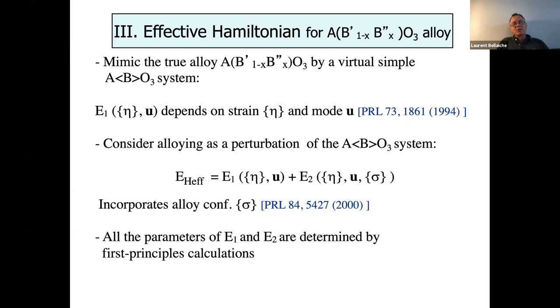And then we said, no, this is not good. I mean, you have titanium and zirconium ions for real. You don't have a mixture between these two guys. So you put a second term. This is the energy E2 that basically characterizes the true alloy represented by sigma. If sigma is plus one, it is, let's say, titanium. If sigma is minus one, it's zirconium. And so you have a perturbation of your virtual system. And the nice thing about that is that all the parameters of E1 and E2, you can get them by first principles calculations. You need to have a code that basically does VCA. It's very easy. We also suggested how to do it with David Vanderbilt. And then you put some perturbation there and you get the parameters of E2.